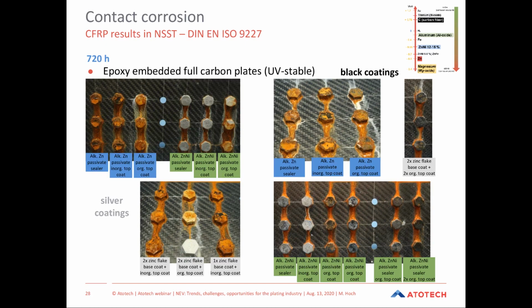Finally, after 720 hours, all systems in our test showed red corrosion. Even the zinc nickel parts and those plated with a CP combination showed severe red corrosion.